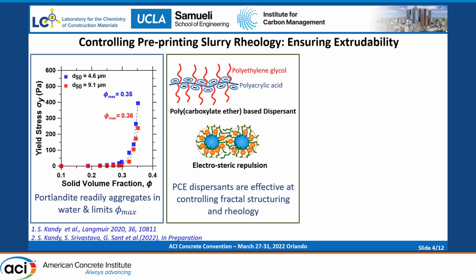So what we did is, for these kinds of suspensions where we have high ionic strength and high charge screening behavior, polycarboxylate ether based dispersants are very effective. These dispersants can induce an electrosteric repulsion between these particles, and basically we can mitigate the particle aggregation.